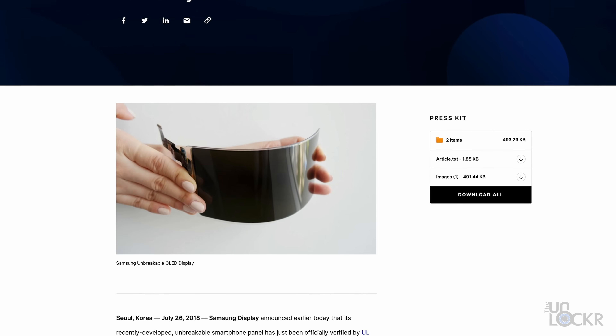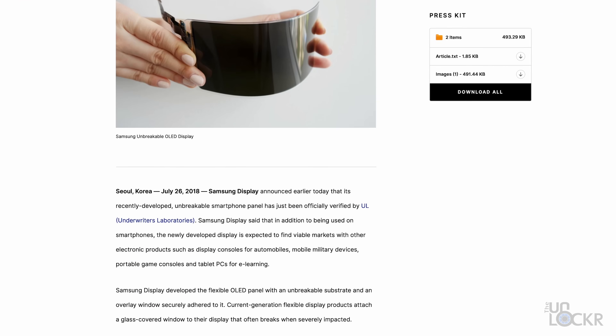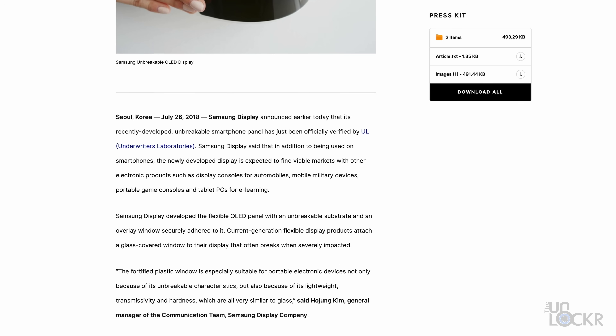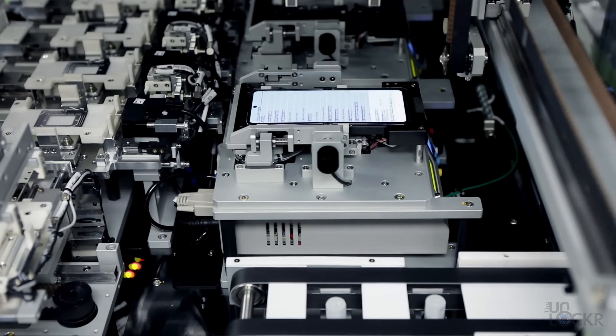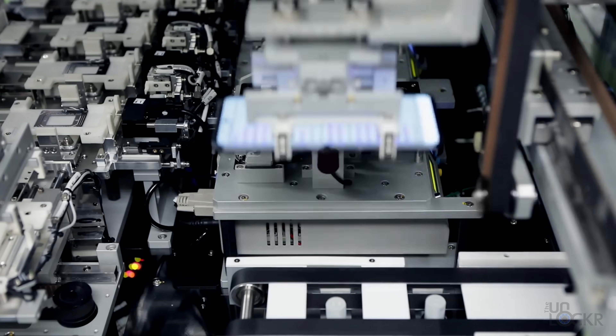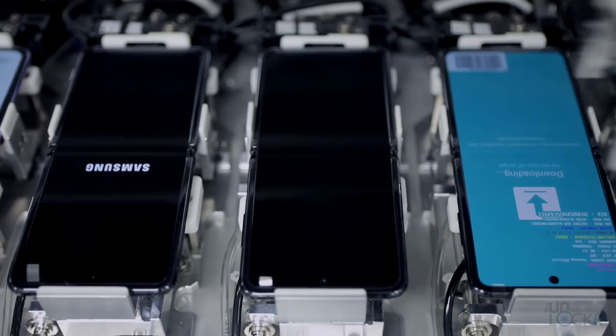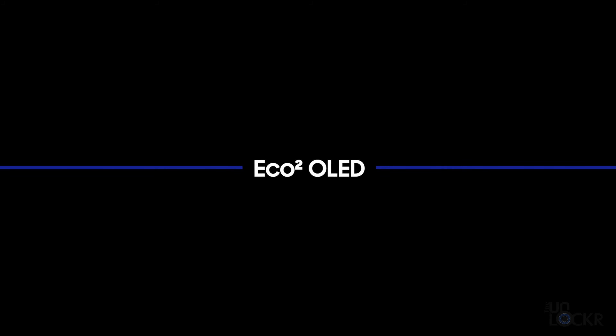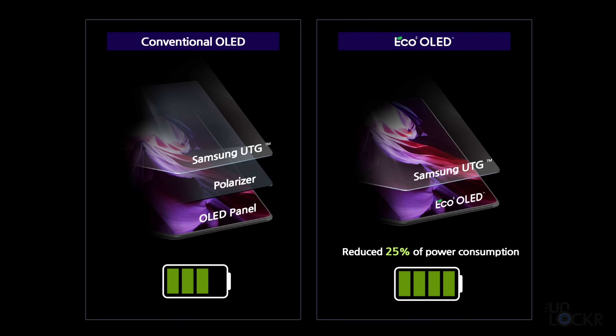Then in 2019, Samsung commercialized a flexible anode layer, a flexible polymer outer layer, and a clear adhesive to hold all the layers together — and at that point, the original Samsung Galaxy Fold was born. In 2020, the Samsung Galaxy Z Flip introduced ultra-thin glass, or UTG, to replace the polymer outer layer, bending simply because of how incredibly thin it was, which was then added to the Z Fold 2. Then in 2021 with the Z Fold 3, they used a technology called Eco OLED to remove the polarizer and combine its effect into the display itself, making the stack even thinner.